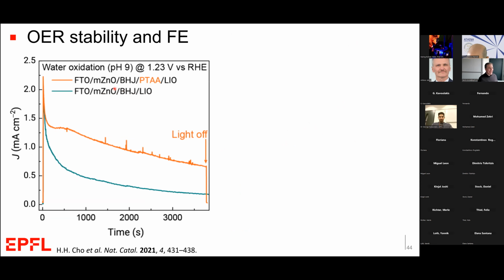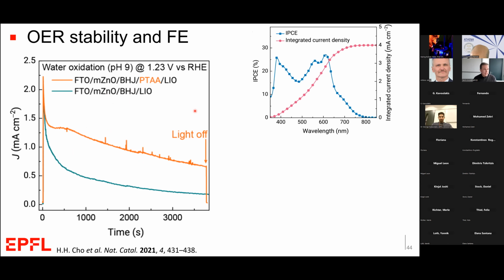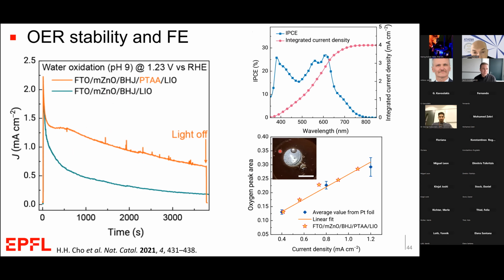Without the PTAA layer that extracts the holes, the performance drops very quickly. But with the PTAA layer, we extend the performance at least for a few minutes before it starts to drop off. And again, we can measure the quantum efficiency and the gas production here to show that we have a high Faradaic efficiency, close to 100% for the oxygen evolution, at least in these initial stages.